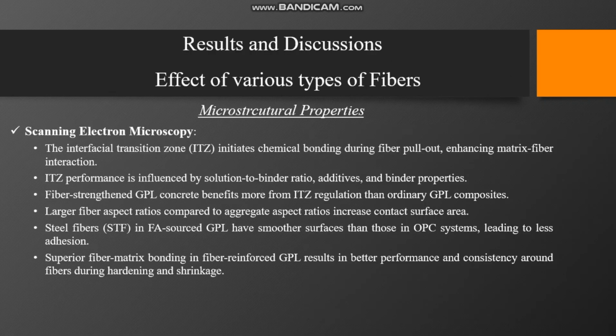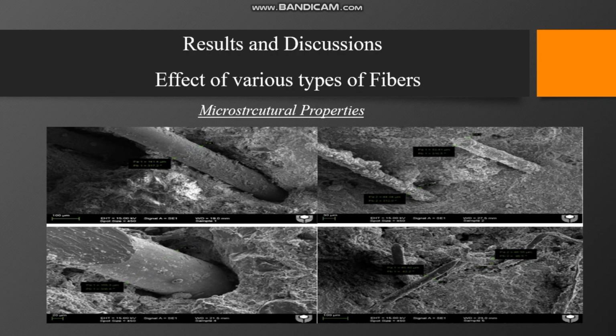Next, we have the microstructural properties. We will discuss them, and first of all we will discuss the scanning electron microscopy. The interfacial transition zone initiates the chemical bonding during the fiber pullout, enhancing the matrix fiber interaction. ITZ performance is influenced by the solution to binder ratio, additives, and binder properties. Larger fiber aspect ratios compared to the aggregate aspect ratios increase the contact surface area. The superior fiber matrix bonding in fiber reinforced geopolymer results in better performance and consistency around the fibers during the hardening and the shrinkage, as you can see in these figures here.